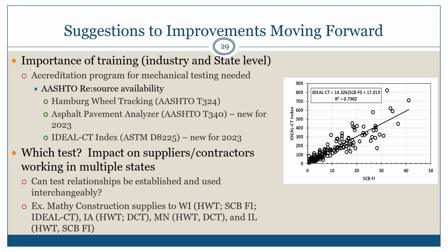With that thought on accreditation, you can see here that there's a very short list of what tests AASHTO resource actually has accredited right now. Hamburg wheel tracking, which has been on the list for quite a while, the Asphalt Pavement Analyzer, and the IDEAL-CT have both been added in 2023. But this is only 3 of the list of over 12 to 13 performance tests that some people are utilizing across the country. So there needs to be a greater push and urgency to get an accreditation program to make sure that both the technicians and the equipment are properly trained and calibrated to ensure that we're getting accurate results.